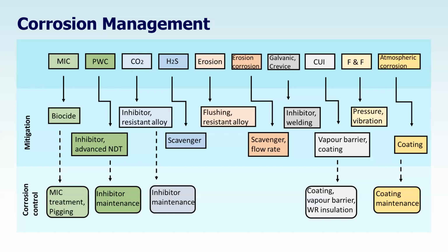Crevice corrosion is mitigated, where possible, by welding and avoiding bolt joints. CUI is the hidden corrosion that happens under the insulation, which will be mitigated and controlled by applying a protective coating on the equipment and a vapor barrier on the outer layer of the insulation, and choosing water resistant insulation. Controlling the vibration and pressure of the system will help to mitigate fatigue and corrosion fatigue. Sometimes if we apply some absorbing layer on the equipment, such as rubber pads, it will help to mitigate the fatigue without changing anything in the operational conditions.